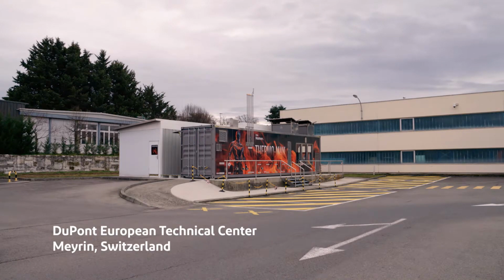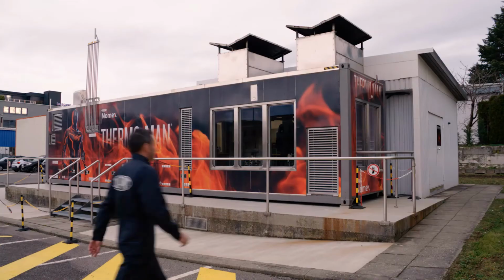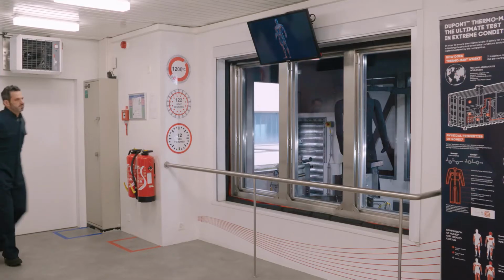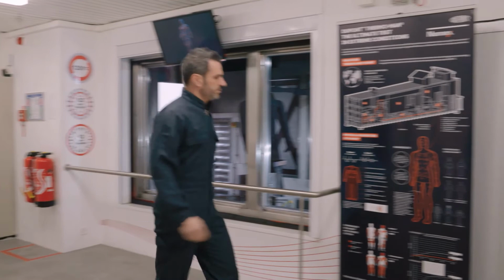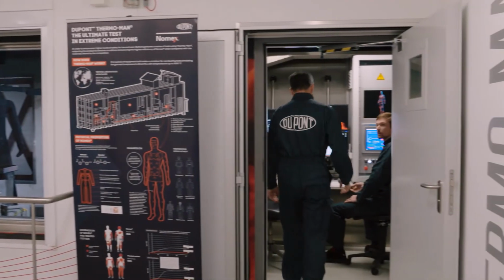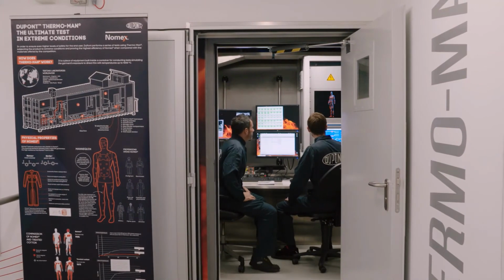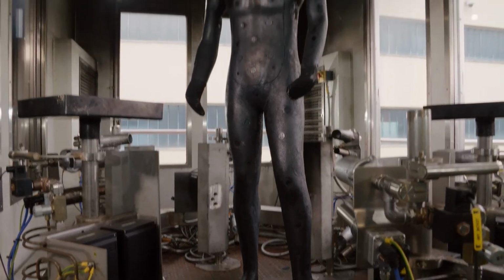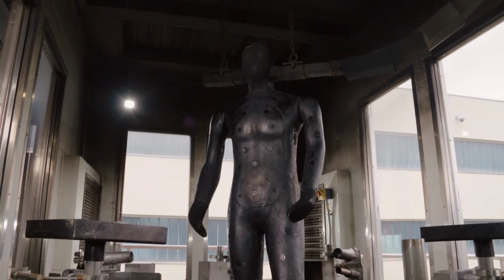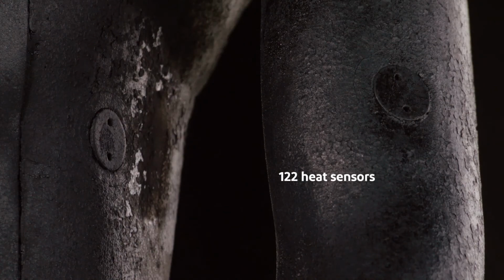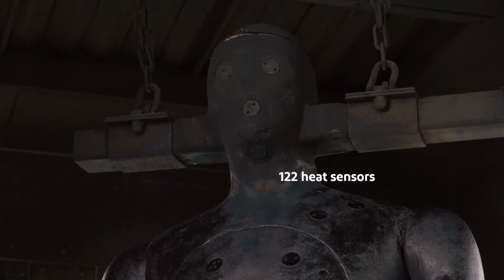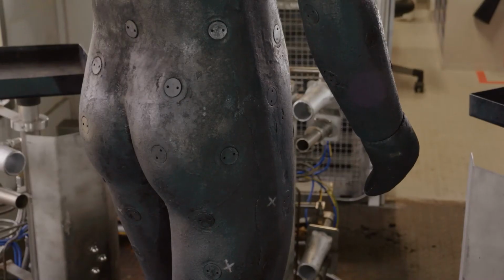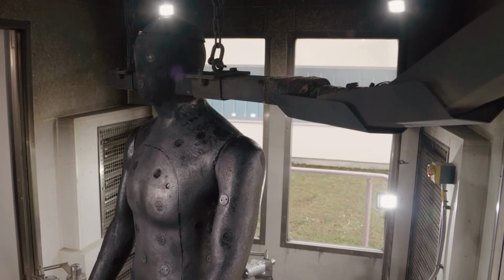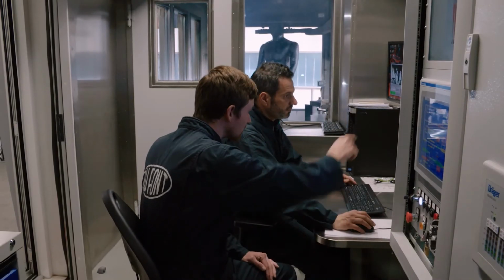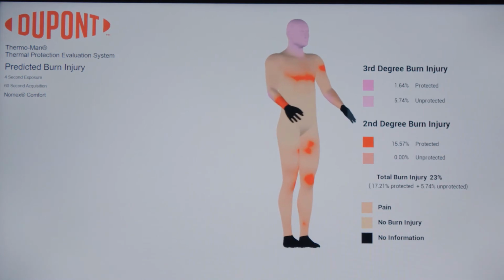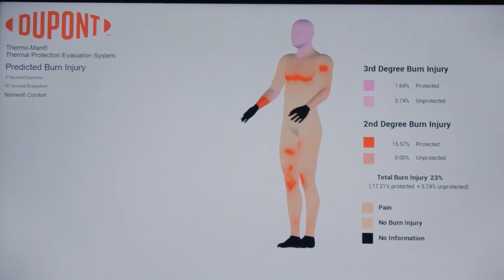Developed by DuPont and the US Air Force, Thermoman is built inside a container for conducting tests simulating the garment's exposure to direct fire with temperatures up to 1200 degrees Celsius. DuPont Thermoman is a life-sized mannequin equipped with 122 heat sensors. The sensors record the temperature rise on the surface of the mannequin. The computer calculates the predicted percentage of second and third degree burn injuries a person might suffer under similar conditions.